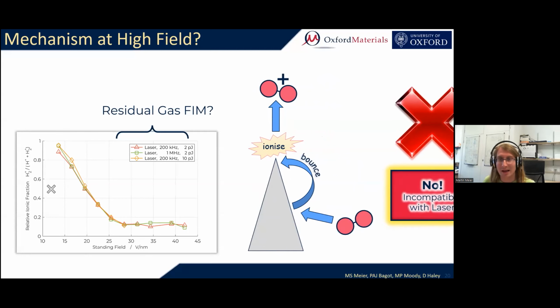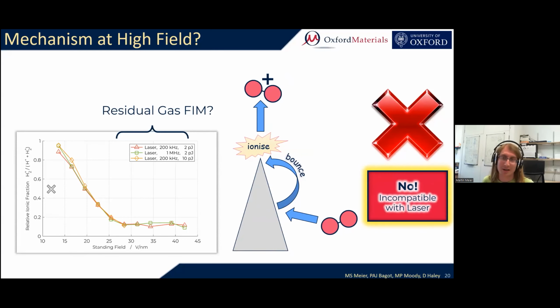However, after thinking about it for a bit longer, I actually came to the conclusion maybe that's not a good theory here, or at least not a good explanation. Because what we know is that the laser is essentially just adding temperature pulses to the tip. I do not really see how a temperature spike in a tip could trigger a tunneling effect of an ion that will ionize a molecule ahead of the tip. And I think that's a major problem, and it probably means that residual gas FIM can't explain what we're seeing here.